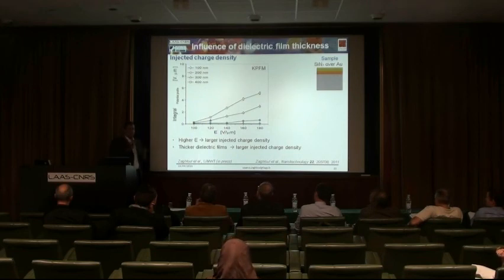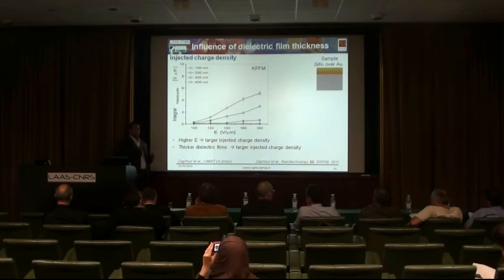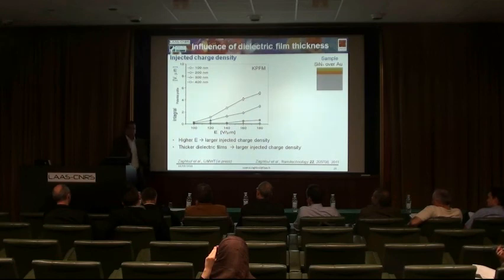You can imagine, if you go for 5 minutes or 10 minutes, which is really short compared to the real device, the decay time constant increases very high and the injected charge density increases very high. I investigated up to 30 minutes, which is very short compared to the real time. So I believe we have to live with it, because we will never be able to overcome it. And the origin for this is electric field and stress time. So this is my personal feeling.